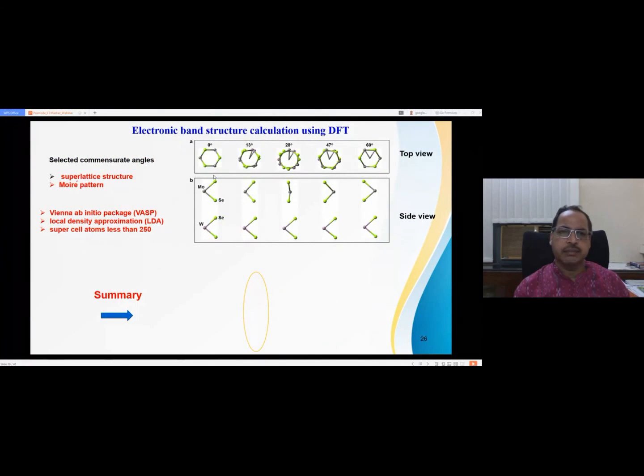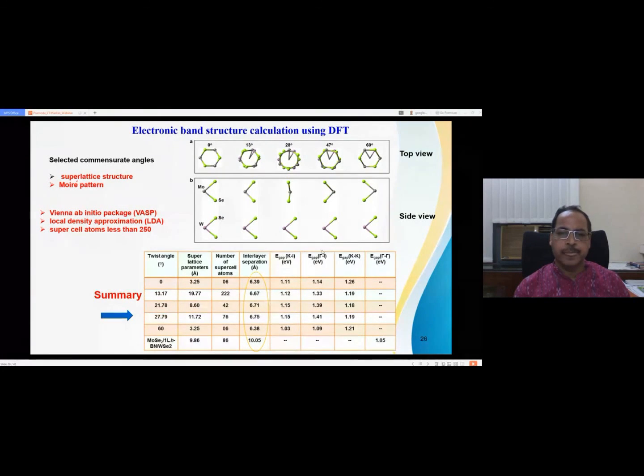Now you rotate this schematic from 0 to 60 degrees. We rotate it, and here you can see the interlayer separation. What is happening in the case of highly symmetric stacking, 0 to 60 degrees? The interlayer separation between the two layers is minimum. Here you can see 6.39 and 6.38 angstrom, whereas in the intermediate it increases. So that is the region where no effective charge transfer exciton is observed in the intermediate angle. We can only see this interlayer exciton very close to 0 and 60 degree angles.